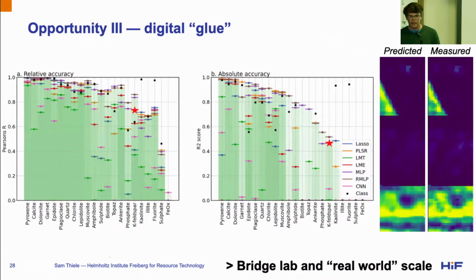Just to expand a little bit on this, as part of this project we did quite a lot of mineralogical upscaling. So we did several hundred MLA to build a training database of the mineralogy of 3 different deposits, and then trained multi-layer perceptron models to predict the mineralogy based on the spectral information.